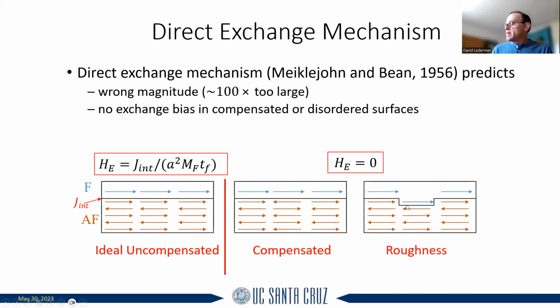And then the other thing that might happen is roughness. We all know that there's no such thing as a perfect sample, and therefore every real sample has some sort of roughness associated with it. Any type of roughness would actually kill the effect, even if you had an uncompensated surface, because you would go from this exchange here, where these antiferromagnetic spins point to the right. If you have a step disorder, then you would alternate between right and left, and the net exchange would be opposite, and it would cancel out. So it was kind of weird, because microscopically speaking, this really doesn't exist. And so the question is, why do we even see an exchange bias in the first place? It's an effect that's pretty easy to measure. You can have exchange biases of 1,000 Oersted or so.